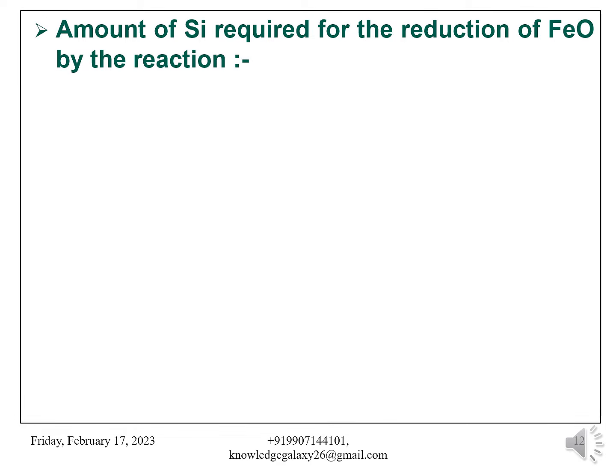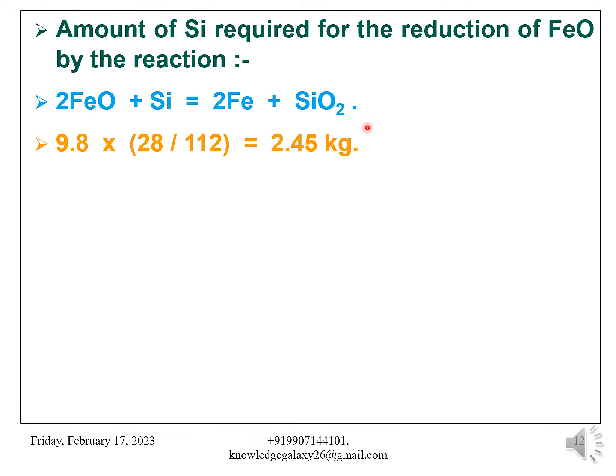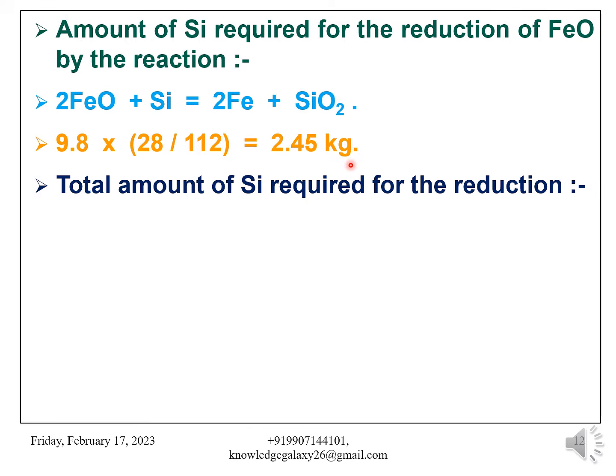Amount of silicon required for the reduction of FeO by the reaction 2FeO + Si = 2Fe + SiO2, and it comes to 9.8 × 28 / 112 = 2.45 kg. Total amount of silicon required for the reduction comes to 12.01 + 2.45 = 14.46 kg.